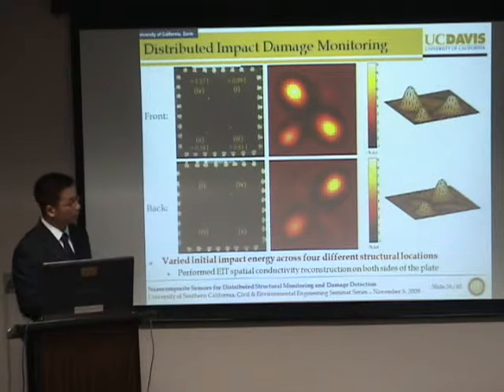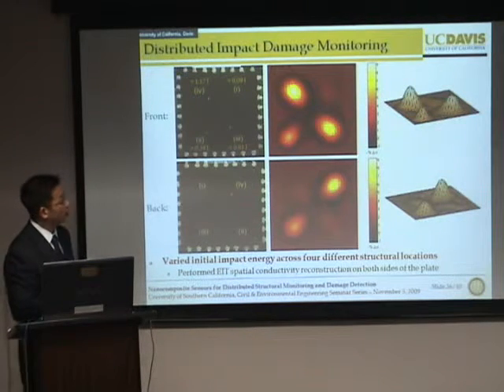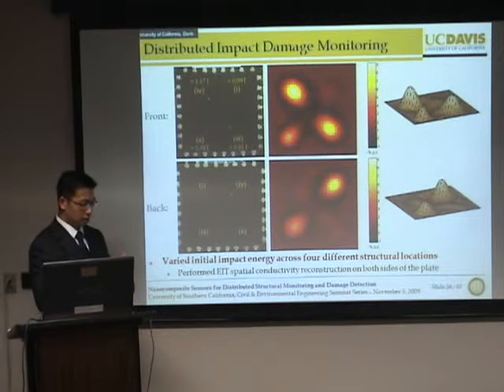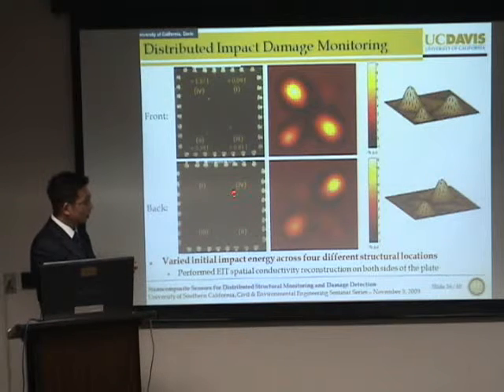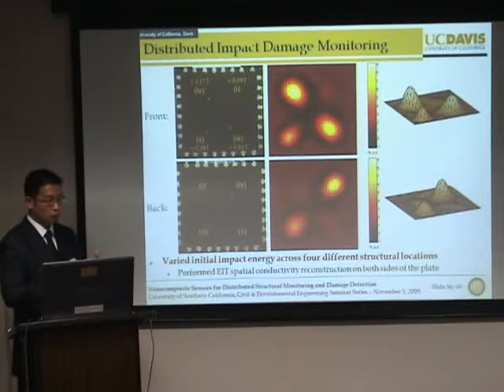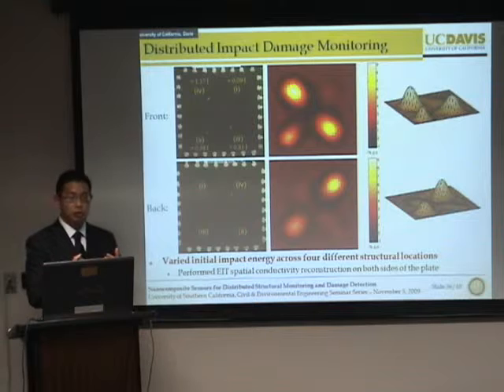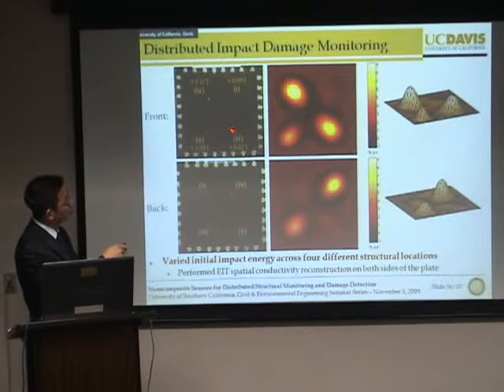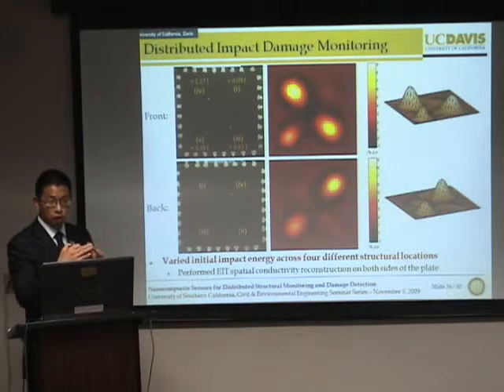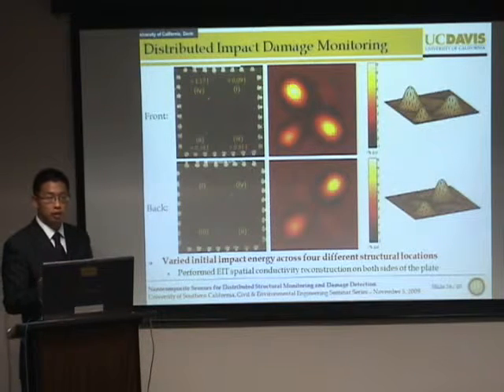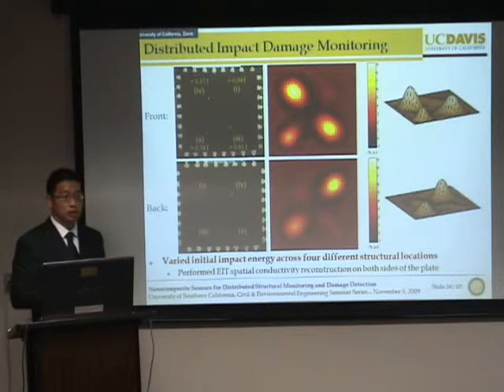But one of the things that we did notice from our study is that when we impact the plate, even though we are physically etching some of the material off, we are imparting so much deformation that we do see some film peeling off of the surface, as shown by the cracking. So this might result in a greater conductivity change in the material at that location.